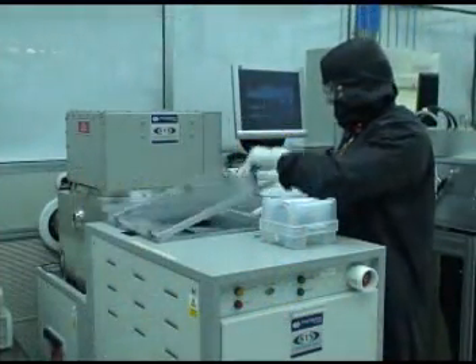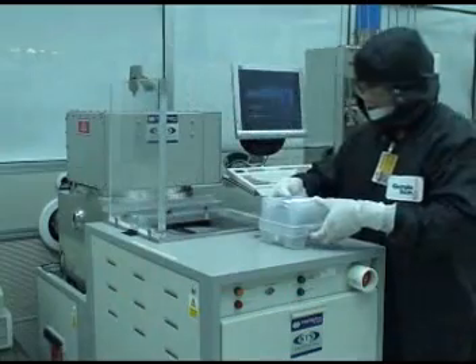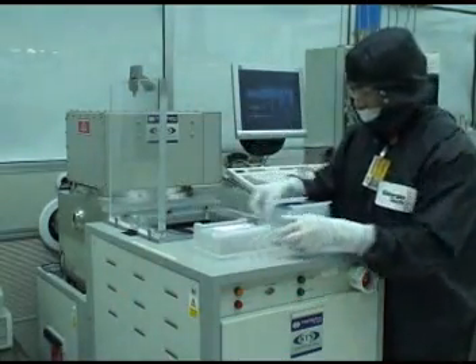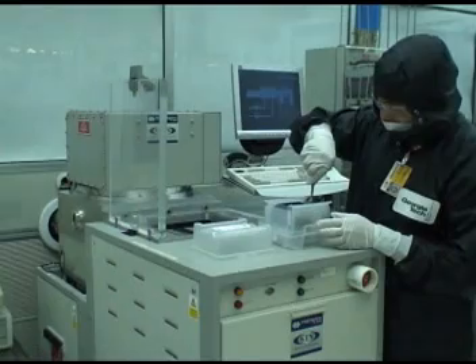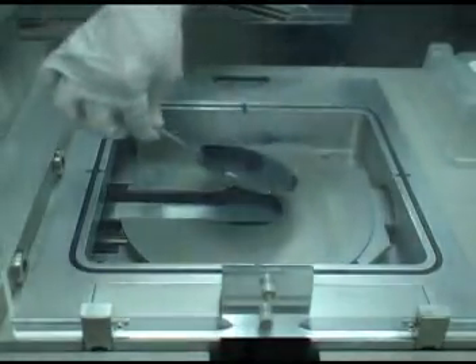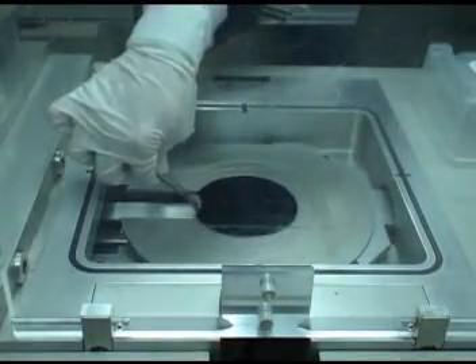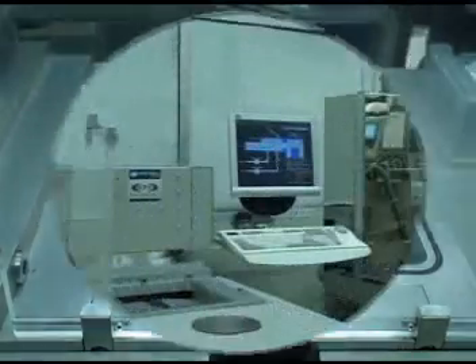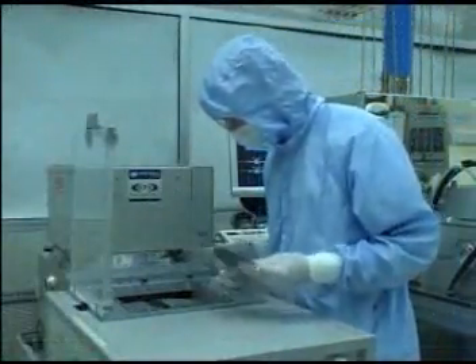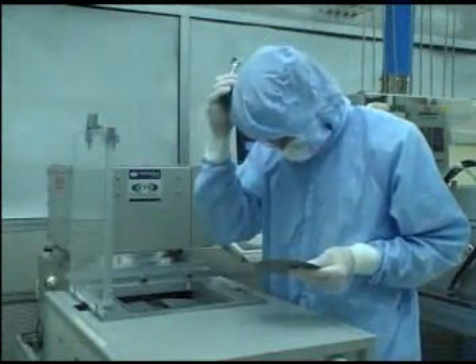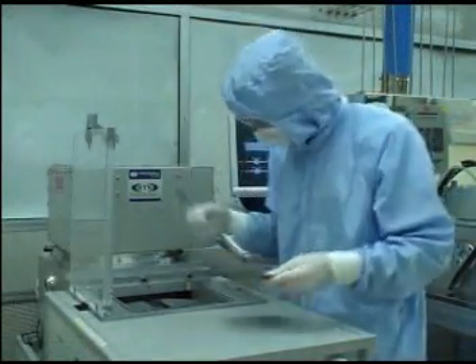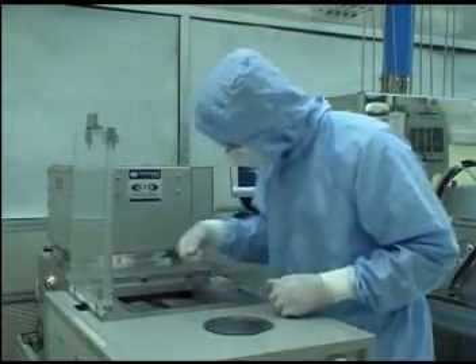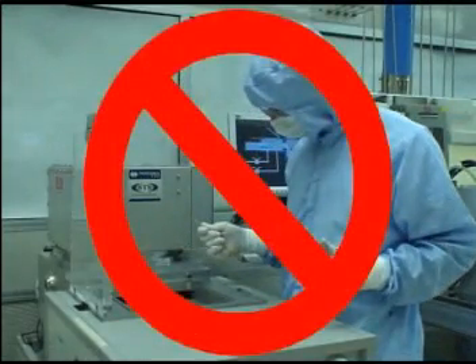Open the load lock chamber lid and place your sample on the tray with the flat edge lined up with the open area in the substrate holder. You should make sure that your sample is securely positioned so that it does not shift during processing. Make sure you use the sample holding plate if you are processing something other than a wafer. Your samples will not be transferred into the chamber if the plate is not used.